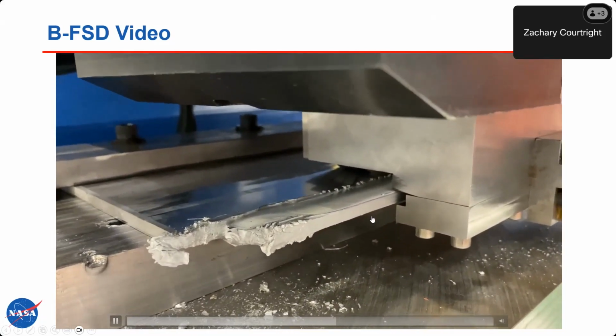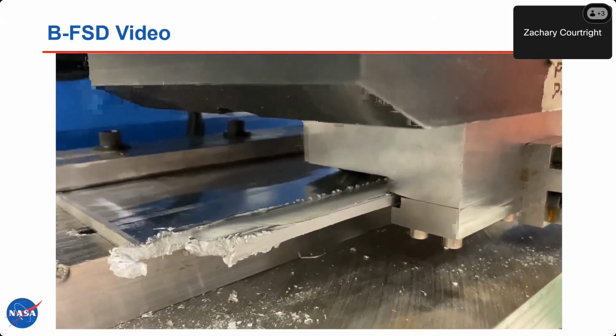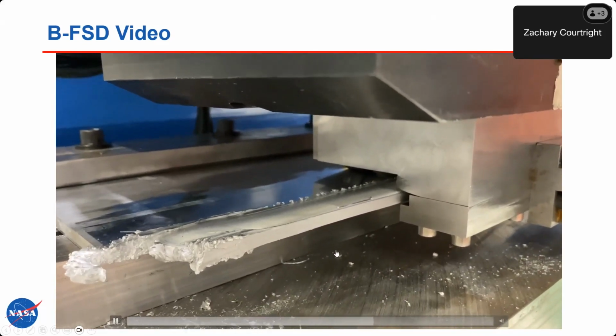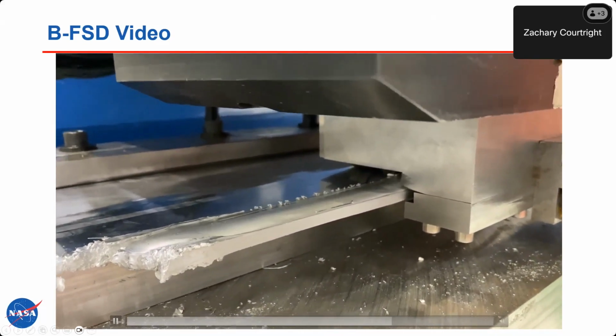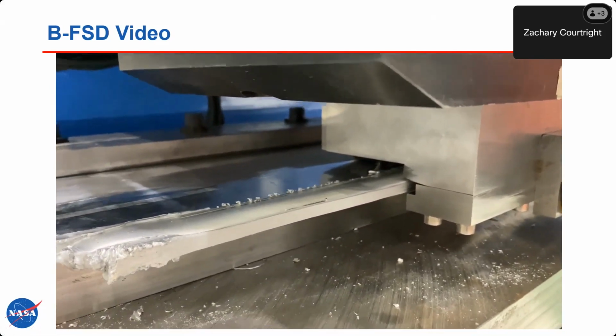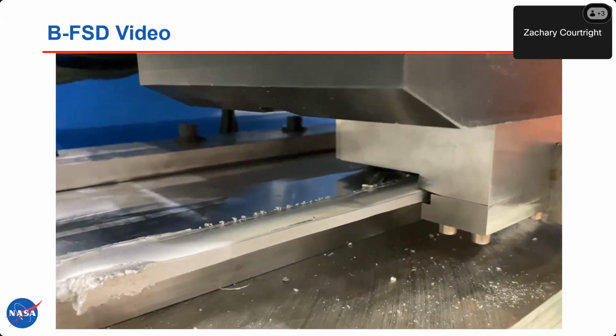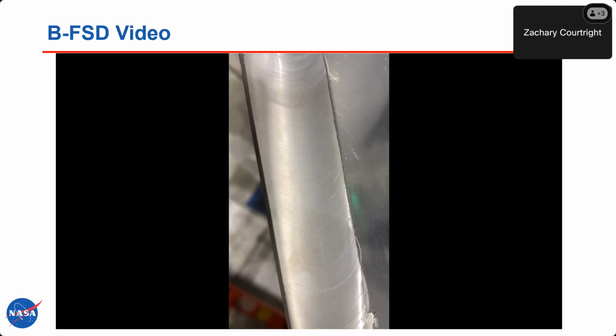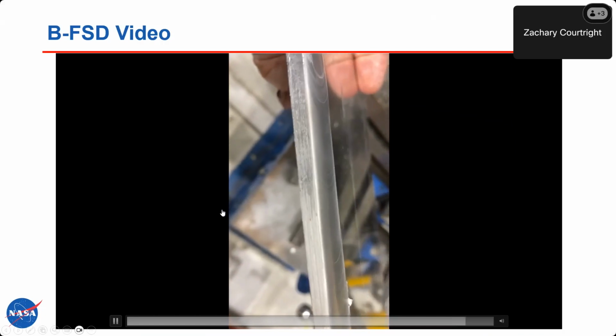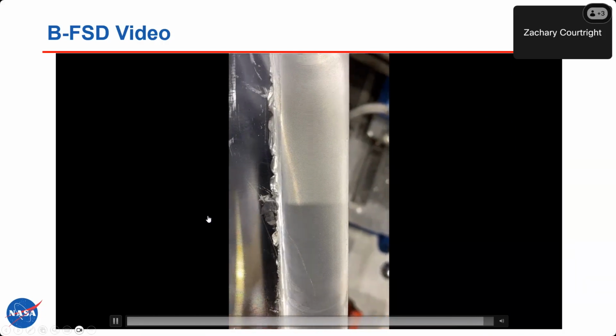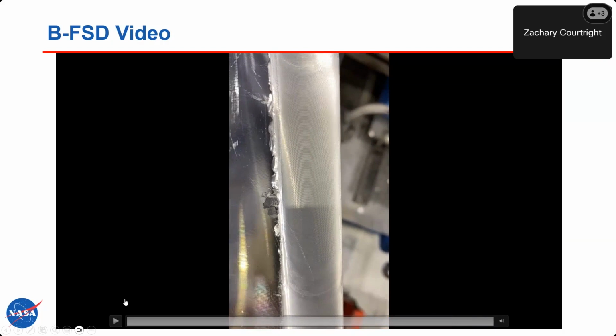That start piece, if you're familiar with friction stir welding, it's typical to have a start block or something like that that would be cut off later. If you were moving in a continuous fashion, you wouldn't have that issue. So this whole steady state region that you're seeing right there is what it looks like, and that plate is as built. You can rub your fingers across it without getting a splinter, but there is a small amount of flash that's inherent to a self-reacting type process. That's something you could easily remove with just a Scotch-Brite pad, or theoretically you could run back over it and it could be reconsumed into the next pass.